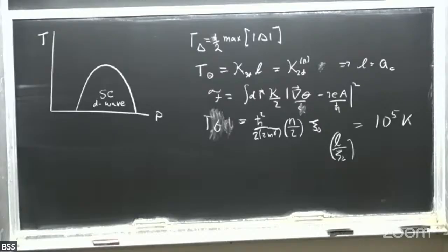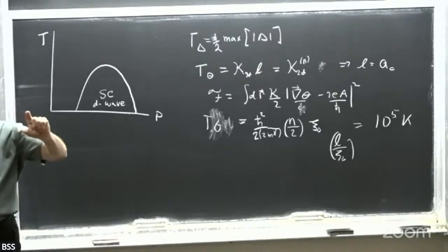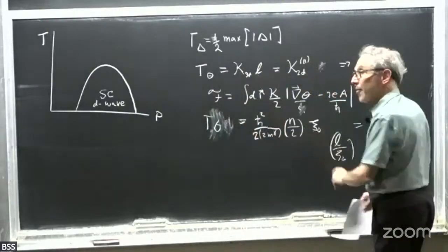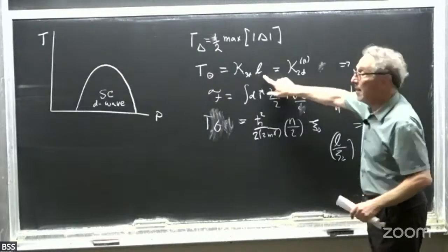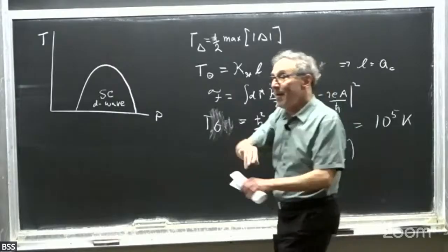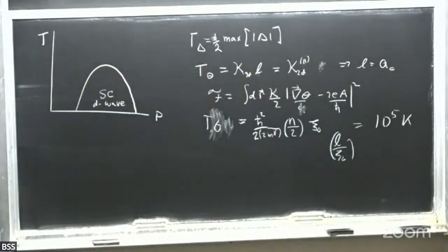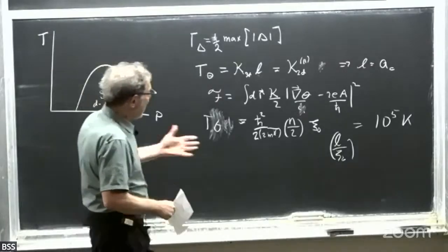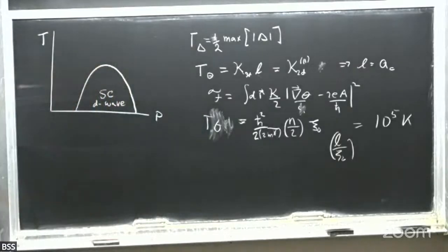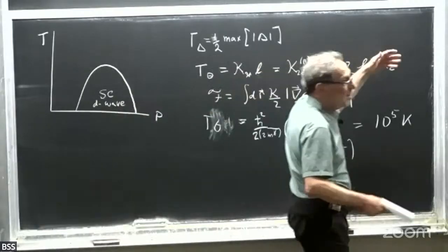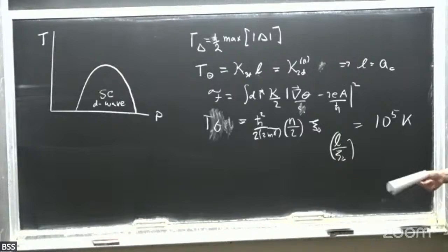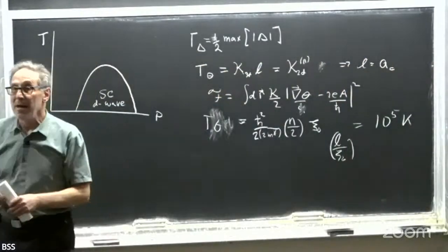Okay? Now, in the cuprates, on the other hand, in the first place, they're quasi-two-dimensional. They're layered. The c-axis coherence length is less than or of order the layer distance between copper oxide planes. So this distance scale here, rather than being a coherence length, is the distance between copper oxygen planes. Each plane more or less behaves like its own phase stiffness reservoir. And the electron density in the cuprate is rather lower than in conventional metals. The lattice constant in the c direction is maybe 6 or 10 angstroms. The lattice constant in plane is something like 4 angstroms. There's only one electron per unit cell.